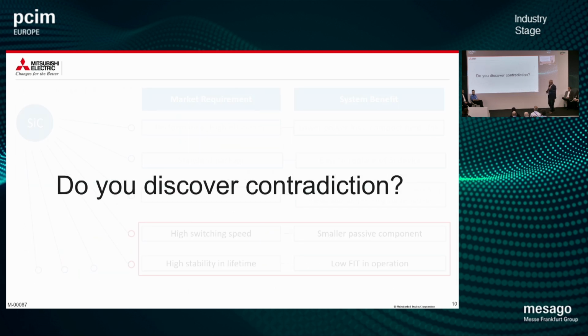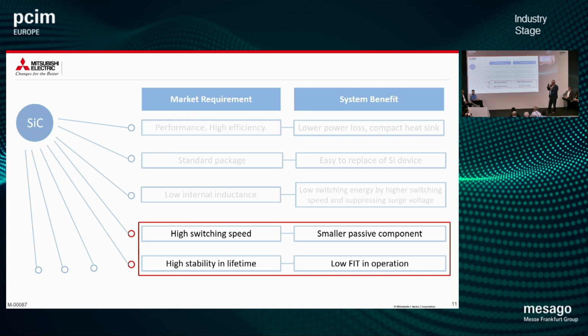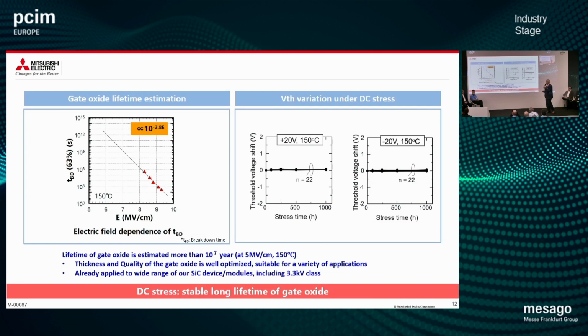What is the next contradiction here? It is for sure high switching speed, or higher stress by electrical field, and high stability in lifetime, which is also an expectation. How to handle this? I would like to distinguish here between DC stress and AC stress, steady state stress and dynamic stress. This is a reliability result of Mitsubishi. First of all, the HALT test, a high acceleration test. In our life, we should handle 5 megavolt per centimeter, and this is our test result, and we will see approximately 10 to the 7 years in operation without sacrificing lifetime. This axis is in seconds, but I think we humans are better off counting in years. It's 10 to the 7 years.